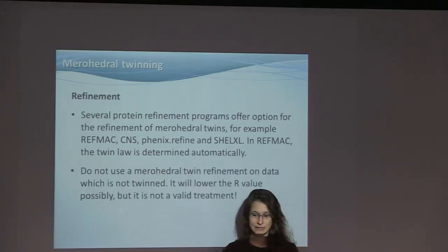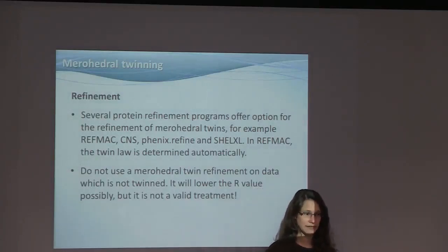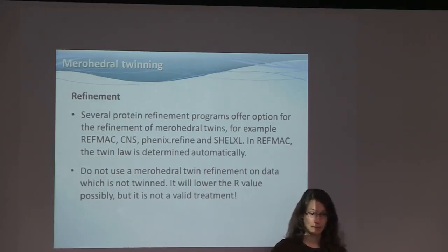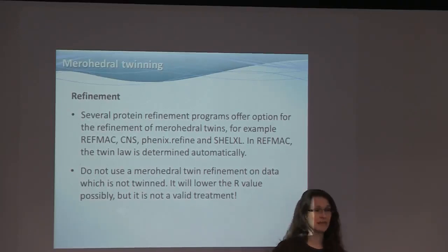For refinement, this is fairly easy these days. Most macromolecular refinement programs support merohedral twins. Some, like REFMAC, find the twin law for you automatically, but you still have to integrate in the correct group.